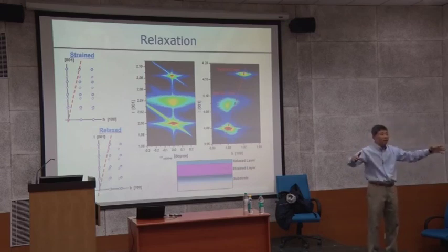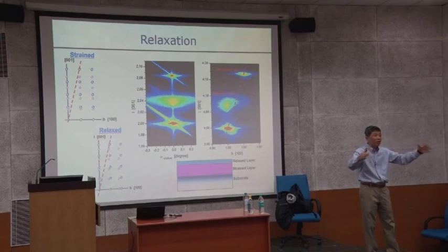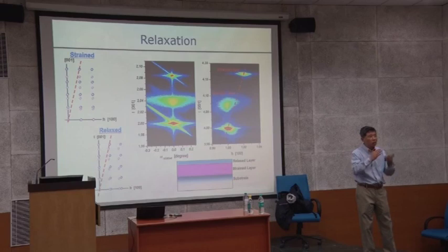But the shape is not symmetrical, and there are many reasons for that. One is coming from the actual reciprocal space shape, which is strain or peak broadening due to thickness or lattice parameter variance, or your X-ray instrument has certain characteristics of the peak.